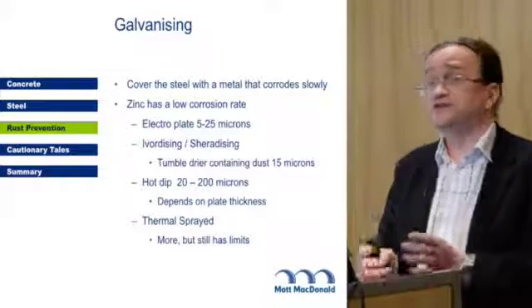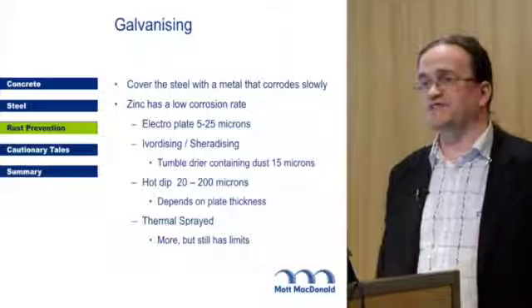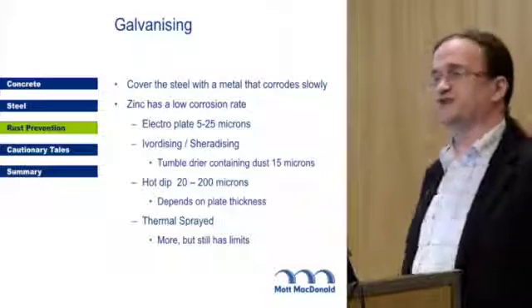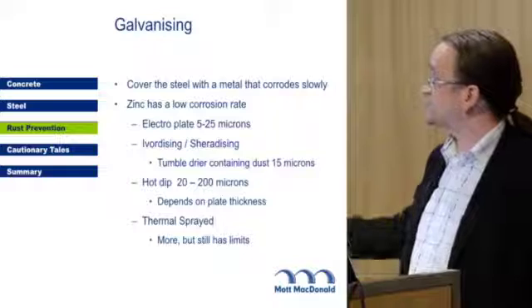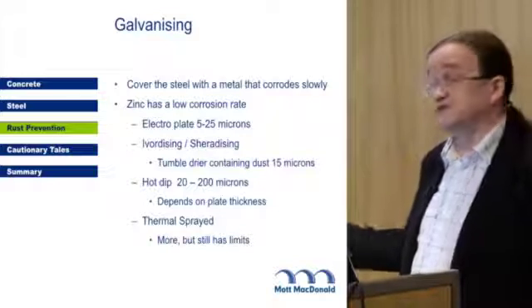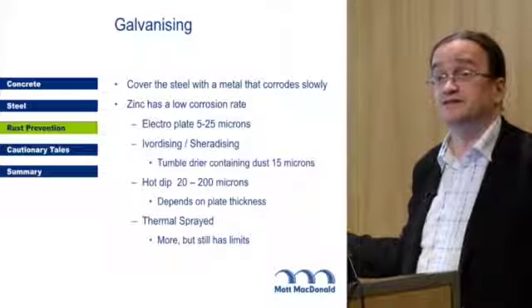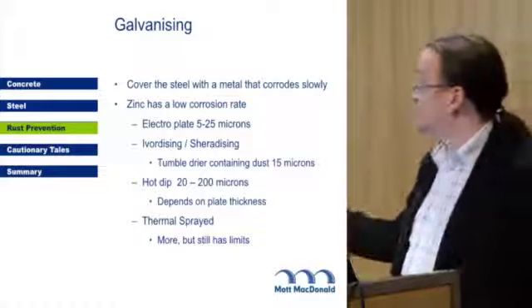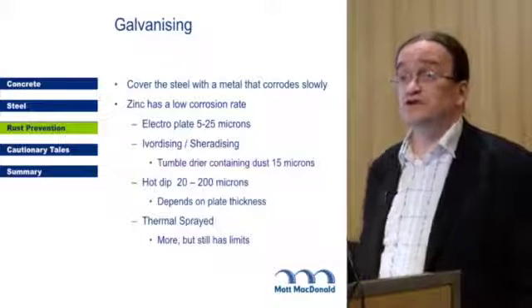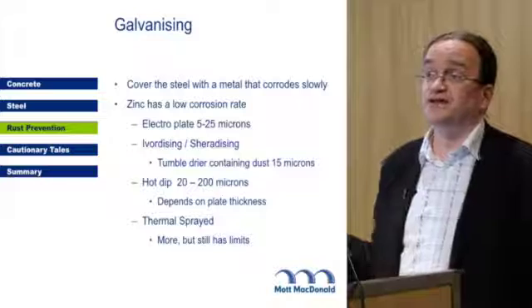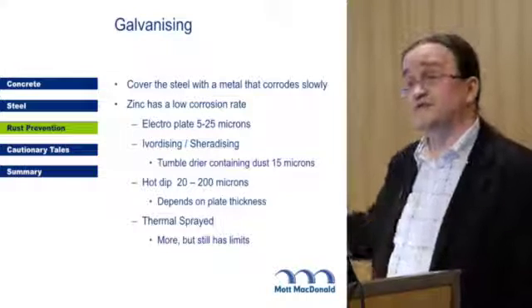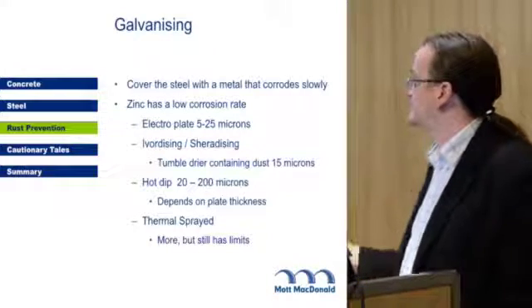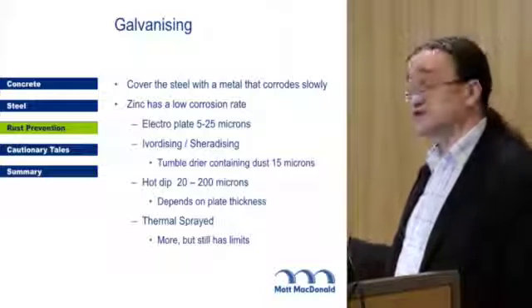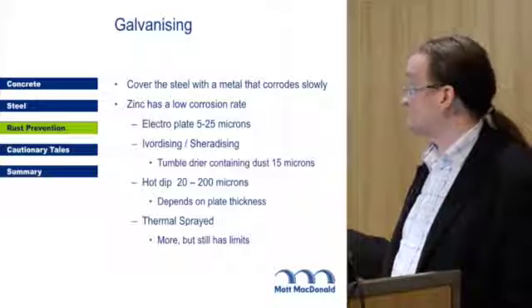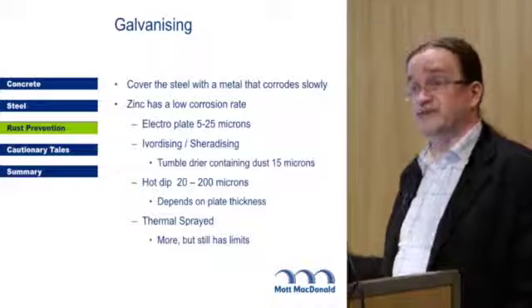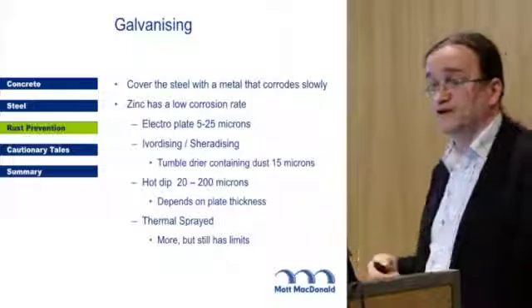Don't look at that 200 and go, right, every spec I write from now on is going to have 200 microns of zinc on everything. How much zinc you can physically get on something depends on the size of the thing you're actually zinc plating. If you hot dipped bolts, it wouldn't work because all the threads would be full of zinc and there'd be no zinc on the shank. So bolts are spun galvanised. It's thinner, but it's good enough. It's the best we can do. You can also thermal spray zinc and sometimes get more than 200 microns on, but it depends on what you're doing and where you're doing it.